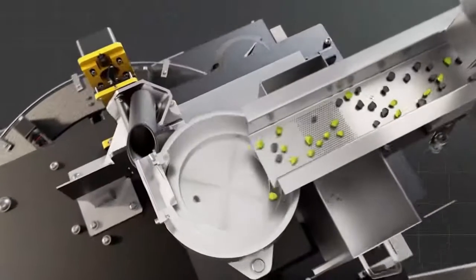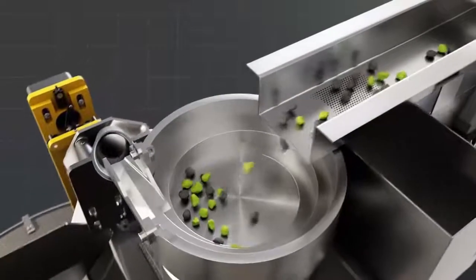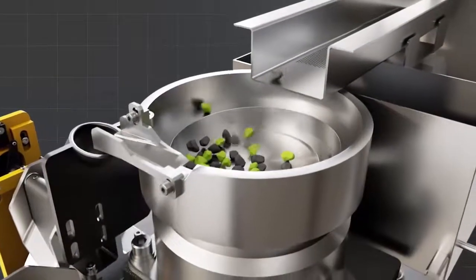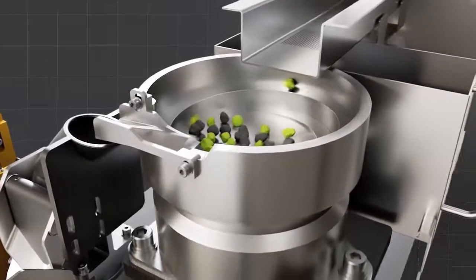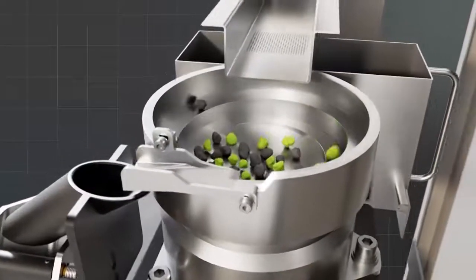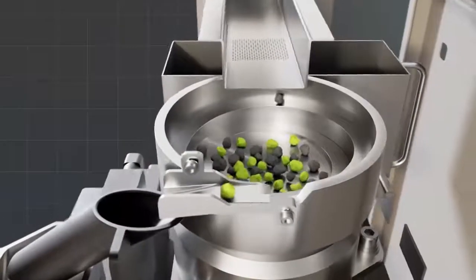Compared to traditional methods like sinkfloat, much smaller samples are required to be representative and provide accurate profiles. In most applications, a sample as small as 1,200 particles would be enough to obtain reliable data.